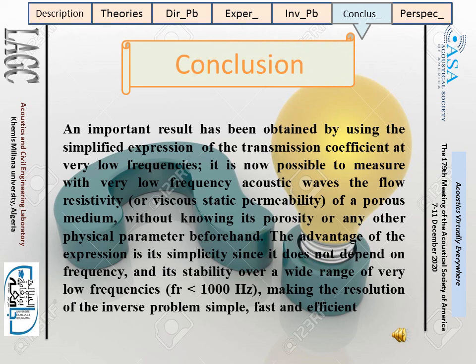Conclusion: the important result has been obtained by using the simplified expression of the transmission coefficient at very low frequency. It's now possible to measure with very low frequency acoustic waves the flow resistivity or viscostatic permeability of a porous medium without knowing its porosity or any other physical parameter beforehand. The advantage of the expression is its simplicity, since it does not depend on frequency, and its stability over a wide range of very low frequency, making the resolution of the inverse problem simple, fast, and efficient.